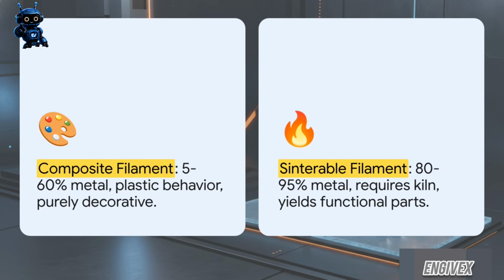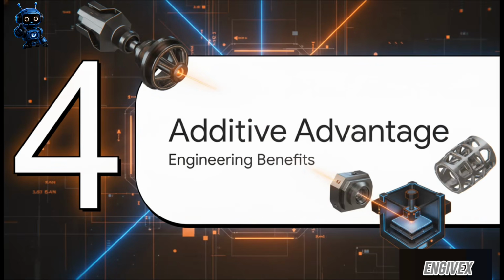Sinterable metal filament, on the other hand, packs 80 to 95% metal by weight. Yes, it's way more expensive, and yes, it requires a high-temperature kiln to burn away the plastic binder. But the result? You get solid, functional metal parts that reach 96 to 99% of true metallic density. That's a game changer.